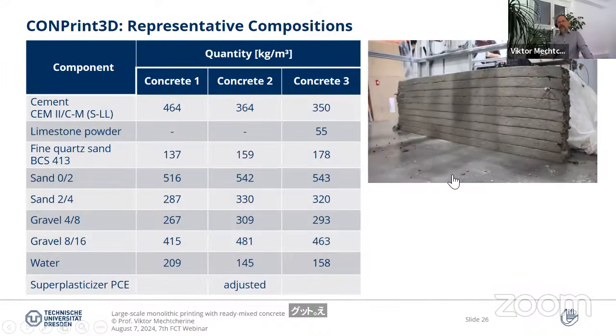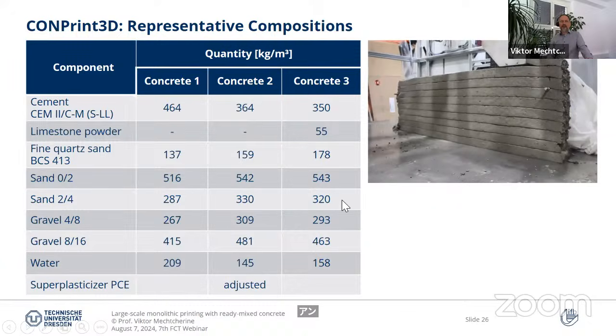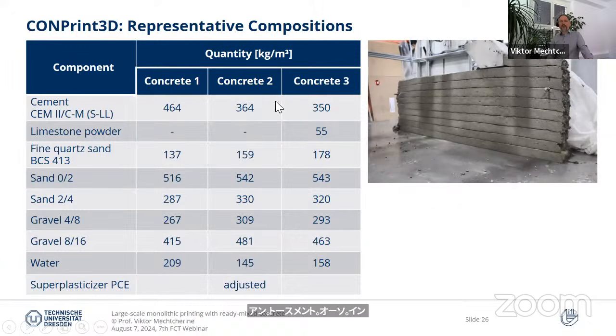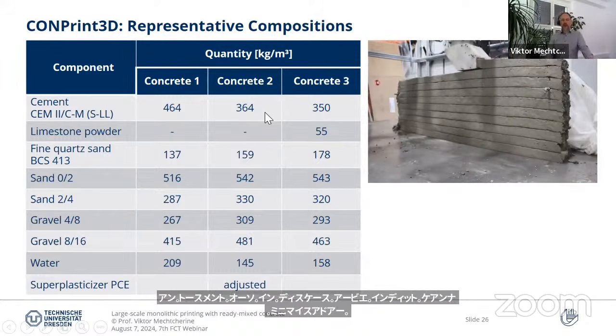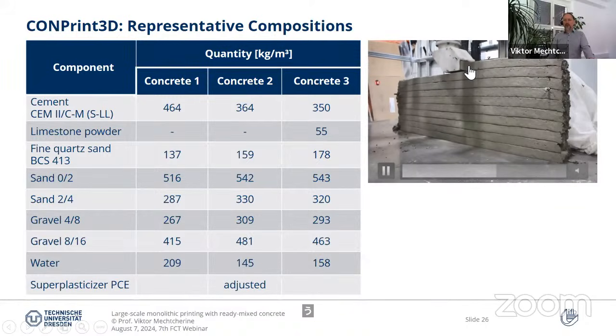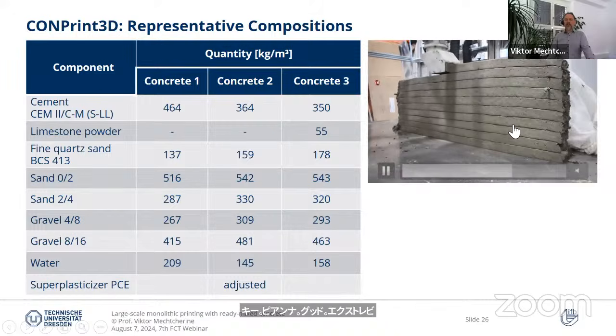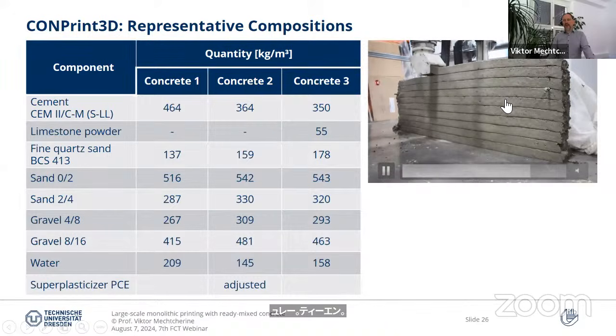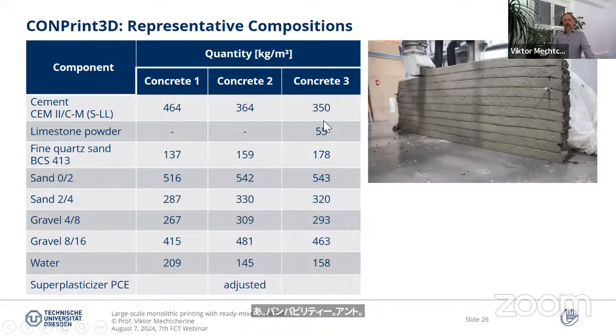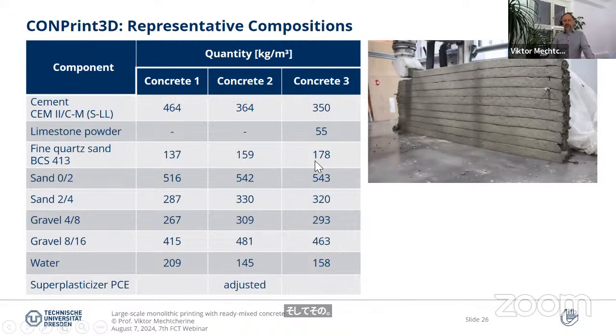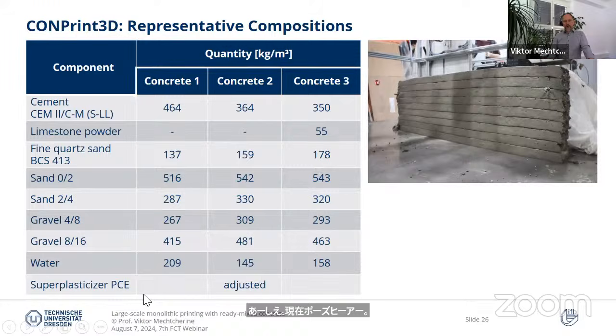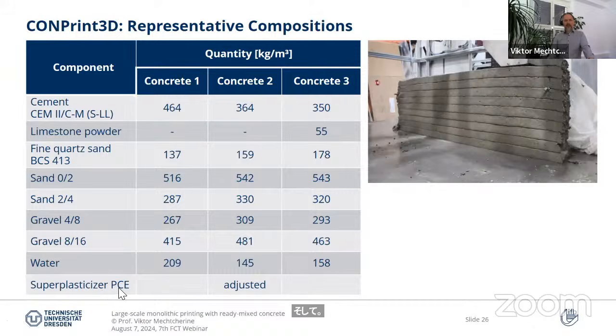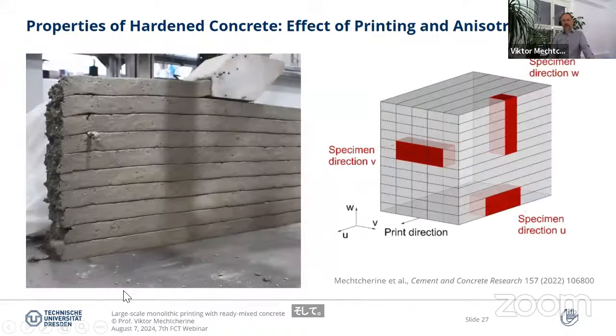And this is what we recommend to everybody. In this case, we indeed can minimize the cement content, while still keeping good extrudability, pumpability, and on the other hand, also buildability. So again, you see some examples here. And we also use some amount of superplasticizer, just again to achieve the rheological properties as required. So now very briefly to hardened concrete.